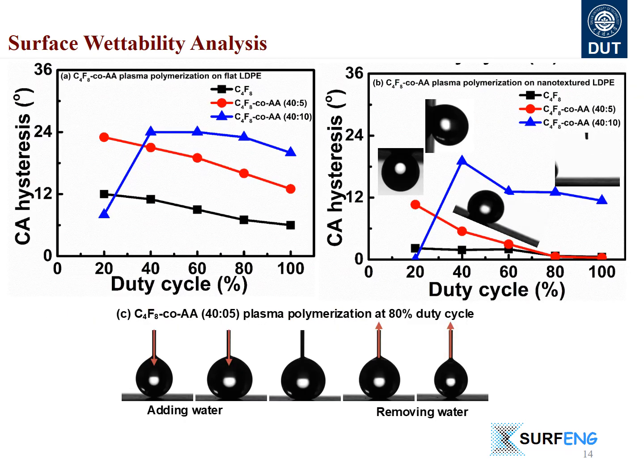With the deep insight of surface wetting properties, it has been shown that contact angle hysteresis can reflect the surface wettability and adhesion more efficiently. The high contact angle hysteresis at low duty cycle is due to the resistance of hydrophilic contents in hydrophobic coatings. This is called surface heterogeneity.